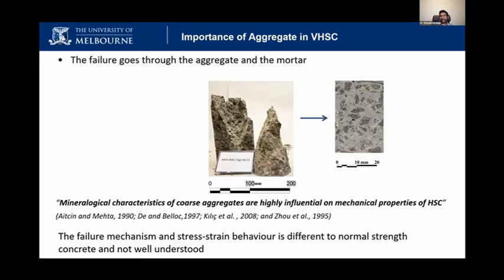Around the aggregate area, sometimes the reaction is not happening properly. Because of that, the ITZ, which means the interface between the binder and the aggregate, is really weak. So the failure goes around the aggregate. But when it comes to high strength concrete, the failure goes through the aggregate. So there's a difference in the failure. From that, we have to understand the aggregate plays an important role in high strength concrete because the failure is going through the aggregate. So the aggregate's strength and its properties also matter to gain higher strength.